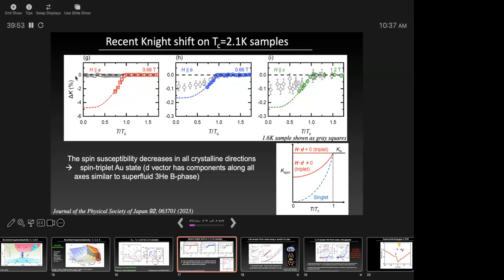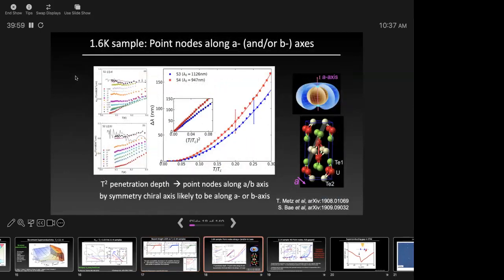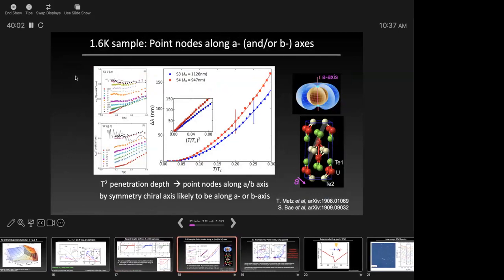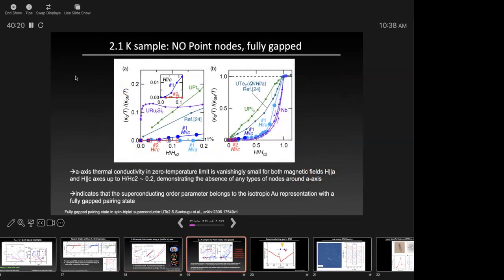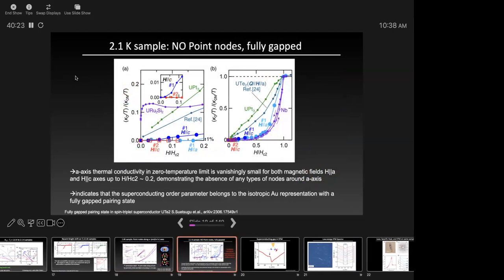Yeah, well, I have nothing useful to say about this. Okay. Yeah, so another thing is that in the initial 1.6 Kelvin samples, the penetration depth showed T-squared behavior, which indicated that there might be point nodes. And now there's the 2.1 Kelvin sample. This is very new data, and therefore I would urge everyone to wait and not jump to conclusions. But at least this data shows that actually there are no point nodes and that it's fully gapped.